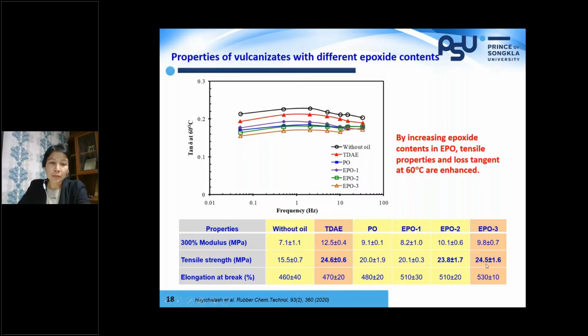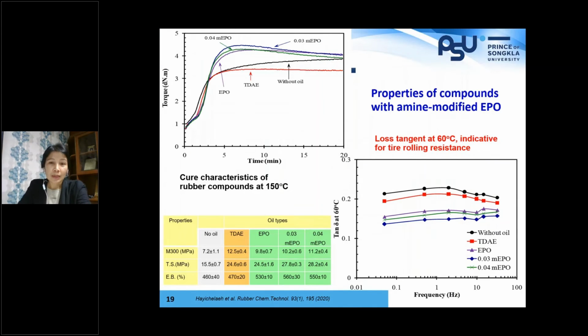Also, on the tensile properties of those compounds, I can show you here that by having EPO with 2 and 3% more epoxide, we end up with similar tensile strength. So for mechanical and dynamic property, we are satisfied with the use of this modified oil. And if we modify further by having amine, then we take EPO also as a control, and we have two different amine modified epoxidized palm oils. Also cure characteristic is improved.